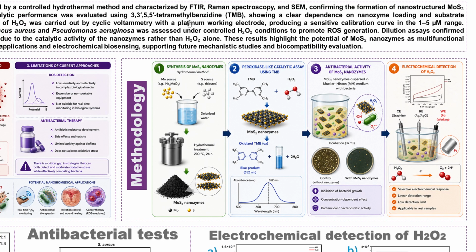As I show in the methodology section, the molybdenum disulfide nanozymes were synthesized using a hydrothermal method at 200 degrees Celsius for 24 hours. We prepared materials using different molar ratios of molybdenum and sulfur precursors, particularly 1:1 and 1:4 ratios, in order to modify their physicochemical and catalytic properties. The resulting materials were characterized using FTIR spectroscopy, Raman spectroscopy, scanning electron microscopy, and transmission electron microscopy.